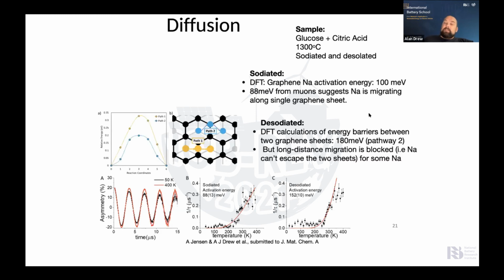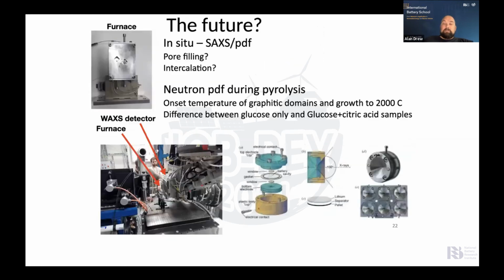This suggests that sodium is migrating along the graphene sheet. For desodiated, the DFT calculations of the energy barriers are about 180 millielectron volts, while we see 150, so it's also of the right ballpark. And the DFT suggests that actually what's happening is that pathway 2 is happening here for the fully desodiated. So long distance migration is blocked. It can't escape 2 sheets for some of the sodium. In other words, when it's desodiated, long migration is blocked. In other words, we have a low mobility site and a high mobility site. And that explains why we get capacity loss in these materials.